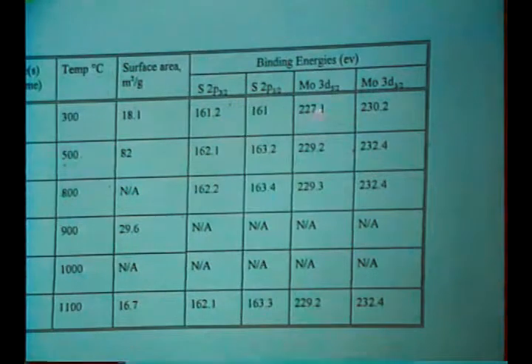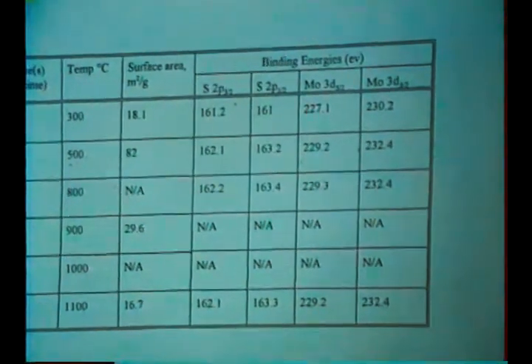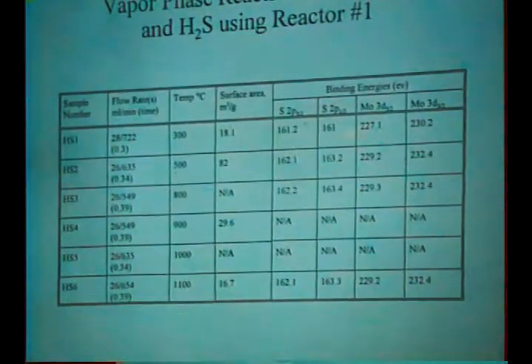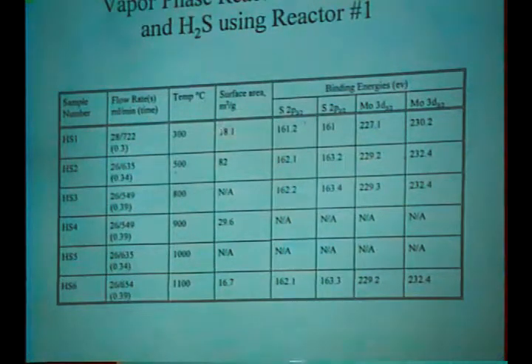What you'll notice more specifically, if you follow the molybdenum 3d energies down, is that the material prepared at 300 degrees centigrade has a binding energy of 227 eV. And as you go to the material that was prepared at 500 degrees, we have a binding energy of 229, which corresponds exactly to that of molybdenum disulfide. So what's happening here is at the lower temperatures, a lower valent molybdenum compound is being produced, as is indicated by the binding energies of the material. And so really what we're seeing here is a transition from some lower valent compound that has a relatively low sulfur amount to molybdenum disulfide. So that explains the anomaly. The decrease in surface area with temperature can be explained simply by annealing effects. And the higher temperatures will anneal the material and sinter the particle size.